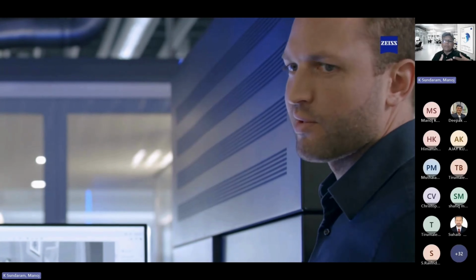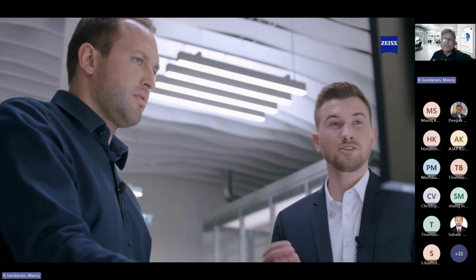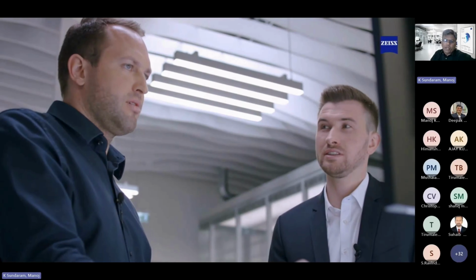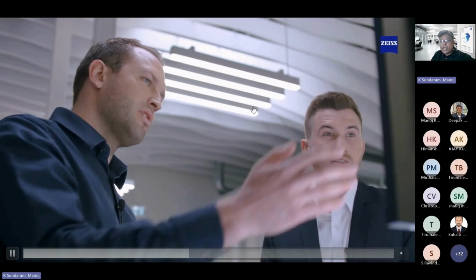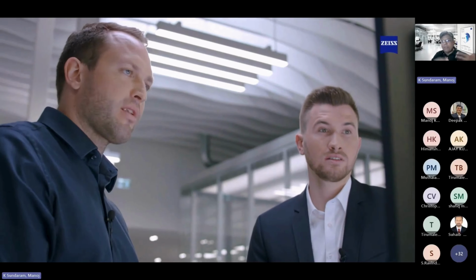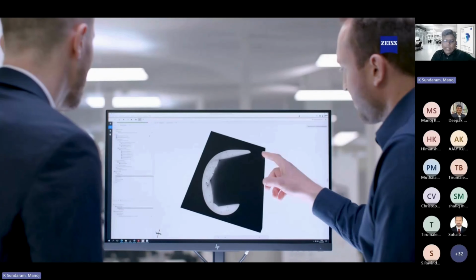So you reverse engineer the part, you know every voxel in the part with a resolution of roughly about 30 to 40 microns. We can go down up to 5-7 micron, but that involves giving it more time, giving it more energy or less energy, depending on the material. Then you get a picture like this.